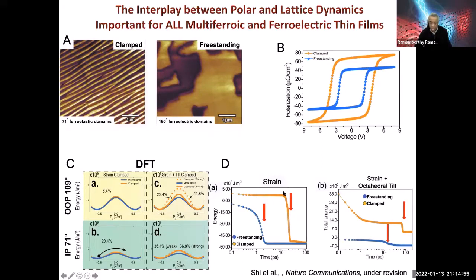Now, mechanics also plays a role in the dynamics of the process. Here are calculations from phase field showing that a freestanding film will switch in about 1 to 2 picoseconds, while a clamped film will take 20 to 30 picoseconds, an order of magnitude. If I include the octahedral tilts, that becomes even stronger. It goes all the way up to about 100 picoseconds. So we need to pay attention when we're looking at these structures, especially switching. You have a time-dependent strain happening in the ferroelectric because the lattice distortion is strongly coupled to the dipole order, unlike in a ferromagnet, which doesn't have that.